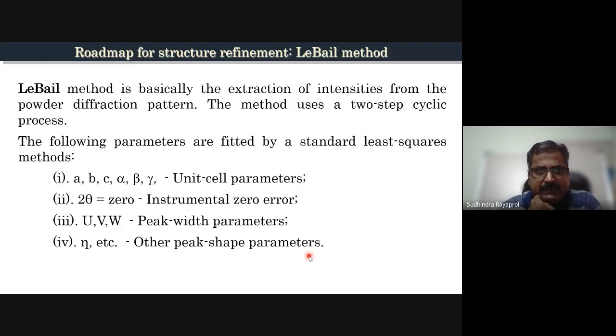The Le Bail method is basically extraction of intensities from the powder diffraction pattern, and it uses a two-step cyclic process. These are the parameters which can be fitted by standard least squares methods: cell parameters, alpha, beta, gamma, and a, b, c values. Instrumental zero error corrections can be done. Half-width parameters can be identified, and other shape parameters can also be fixed. As we will see, Fullprof is basically two parts: one is the instrumental part, one is the sample part. Instrumental parameters can be fitted using the Le Bail fit. Once you fix these parameters, then you are worried only about the sample part.